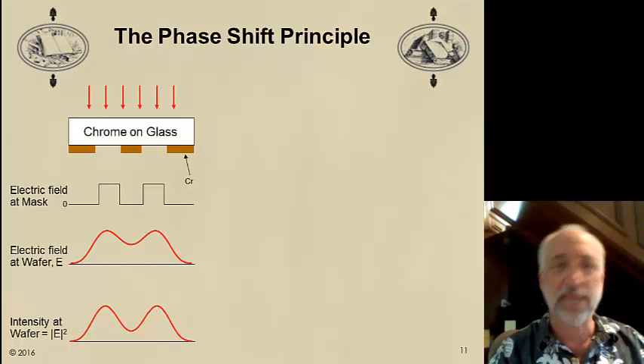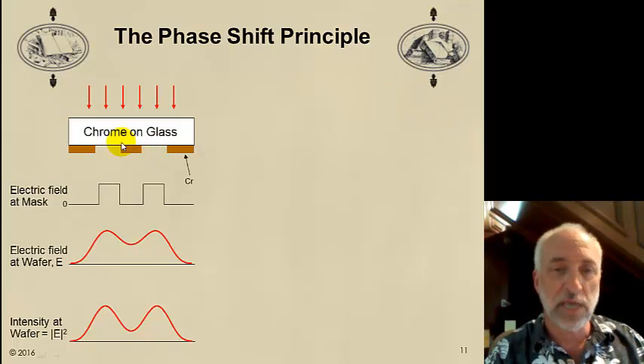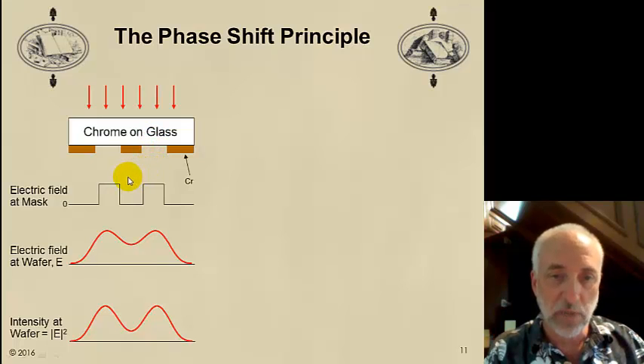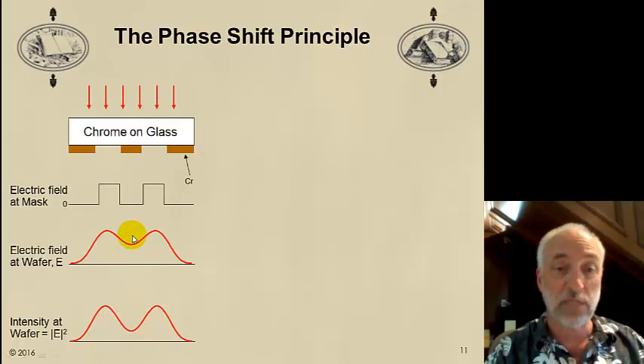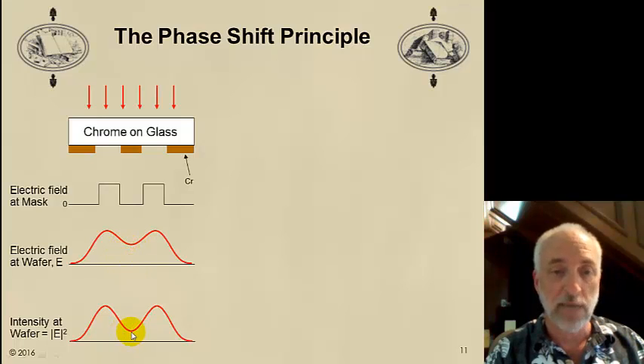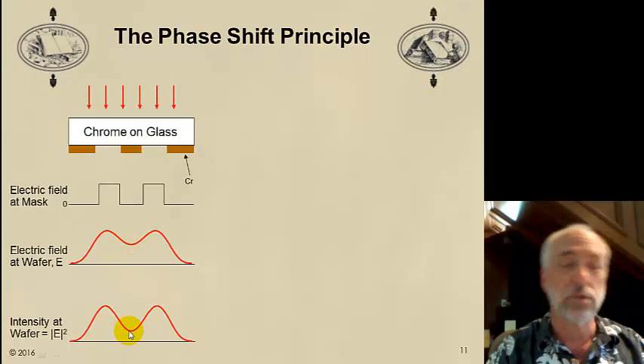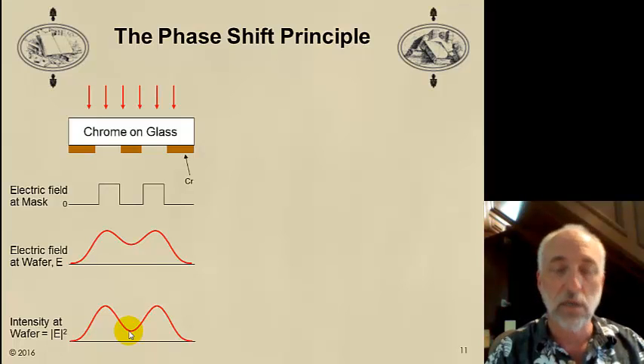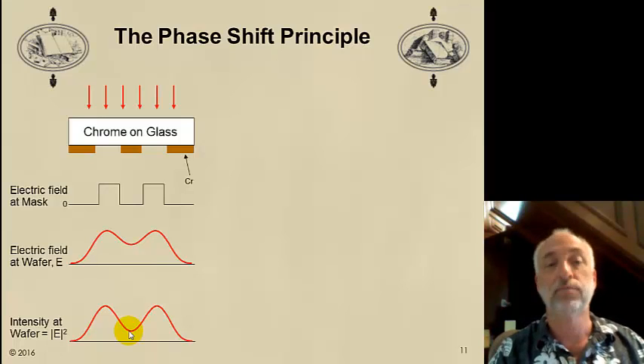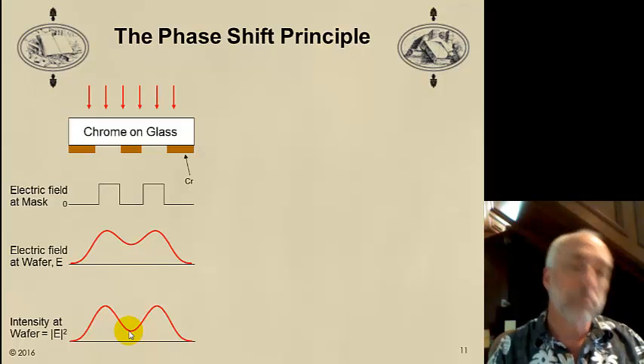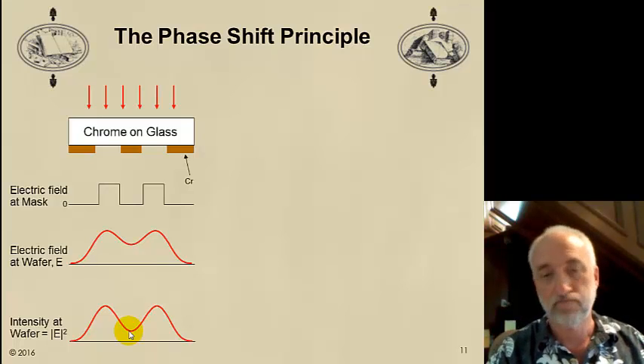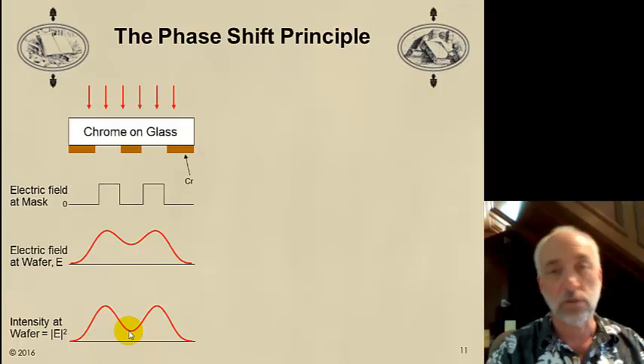A simple way of looking at that is some of the light coming through this space is diffracting underneath the chrome pattern, or where the chrome pattern would be on the wafer, and some of the light coming through this space is diffracted and lands on the wafer underneath the chrome line in the middle. The result is an electric field at the wafer that's bigger than 0 because of this diffracted light. That produces an intensity equal to the magnitude of the electric field squared, which is also bigger than 0. This added light degrades the quality of the image and ultimately limits our resolution.